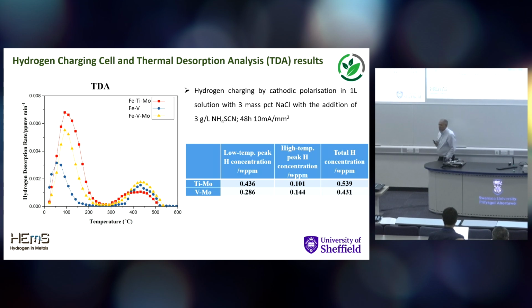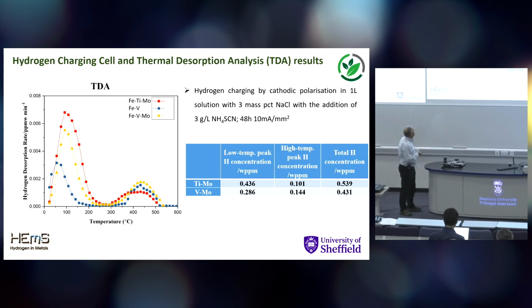One of the few tools that we've got to see where the hydrogen has gone in the lattice is TDA, so it's thermal desorption. So basically we just pump a load of hydrogen into the material, we heat it up over a range of temperatures, and we see how much hydrogen is desorbed at each temperature. The red curve here and the yellow curve are the two steels that I'm going to talk about.